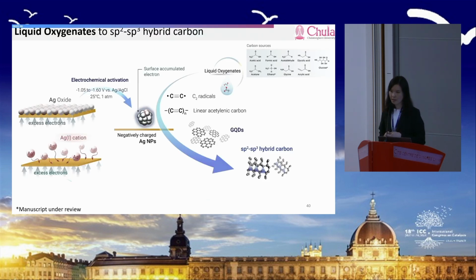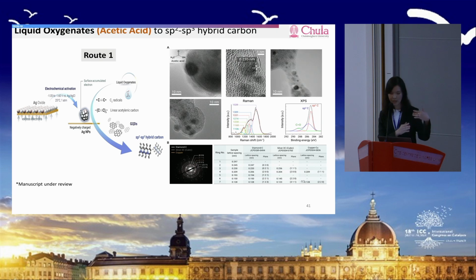And to prove our concept further, the existence of the negatively charged silver, how are we sure to have it? We have the deposited particle before, and we think that they have some oxide layers that we need to reduce to create this negatively charged silver. So if that's the case, it would work when we don't have the pre-electro-deposited particle. We just have the bare copper foil and add a little bit of silver cations. We should be able to get the same thing if the concept is correct. And yeah, this is when we have electrodeposited silver, and then we apply electricity to induce the negatively charged silver. And we were able to make a solid graphene sheet. We see a trace amount of carbon quantum dots on our electrodes, and we see the structure of the carbon.